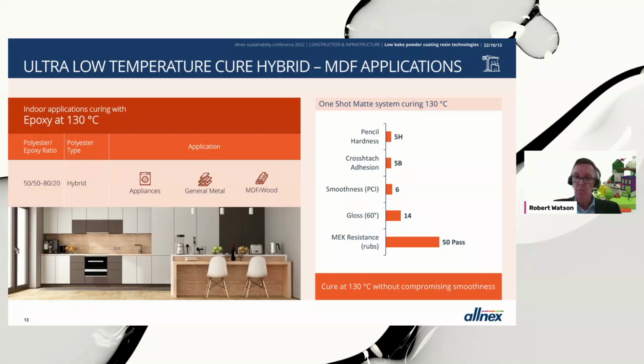And just at the bottom bar there, the MEK resistance, this is a solvent resistance test, which tells us whether the film is cured. In terms of number of rubs, we look for 50 double rubs, which is a standard pass. So we can say for this type of powder coating, we can get exceptional smoothness at 130 degrees centigrade with no loss of cure and no compromising properties. So very exciting that the technology is able to routinely hit the performance criteria at these lower temperatures.